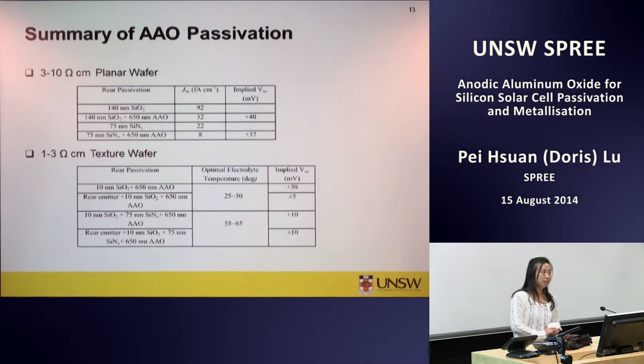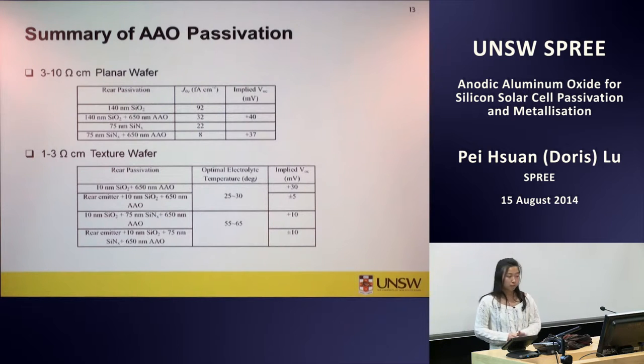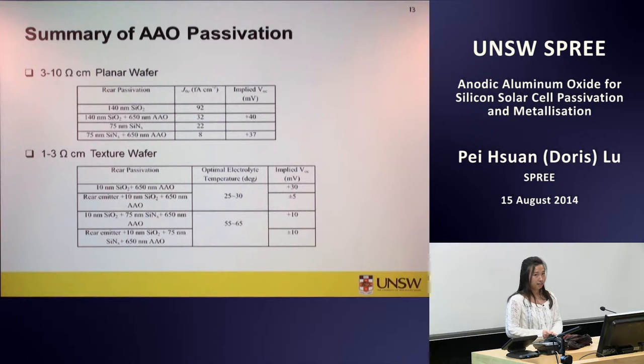So to summarize the AAO passivation, on the planar wafer the improvement is much more predominant. Like on the silicon nitride passivation layer, the J0 value can reduce from 22 femtoamps to 8 femtoamps per centimeter square, and in terms of implied VOC, it can improve by more than 30 millivolt. On the textured wafer, the improvement on the thin silicon dioxide suggests the anodic aluminium oxide could provide a hydrogen source and also enhance the passivation, reducing the density of states at the interface.